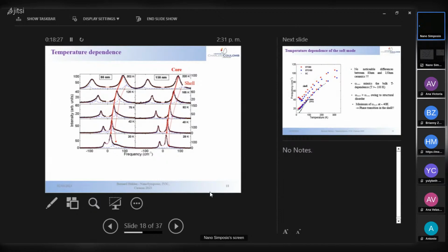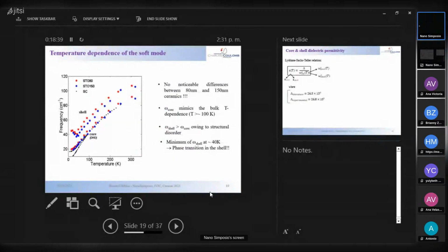So you see the decrease in frequency of the mode with temperature in the core, in the shell, and in the two ceramics we had at our disposal. And so we can now plot the frequencies here. That's the frequency of the mode as a function of temperature for the core and for the shell. In blue for the large grain ceramics, and in red for the small grain ceramics.